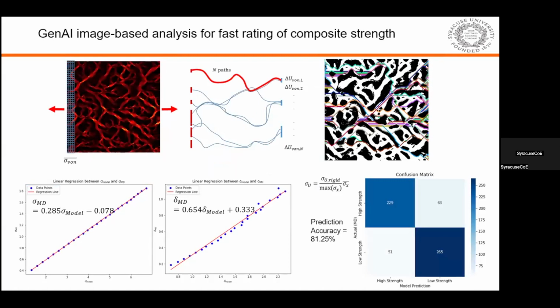So how to use those stress fields? We need to correlate that stress field to material property. We can take the stress field and do the average to calculate the applied stress, and then we can generate many paths, and based on the paths, we take the integral and calculate the amount of displacement. And then once we have the stress and the displacement of the sample, we can calculate the Young's modulus, and we can interpret the ultimate strength and toughness of the material. And then we can also evaluate the accuracy. So this is a confusion matrix between the actual MD result and the prediction from generative AI and the simple algorithm for mechanics calculation, to see that in most cases they agree with the MD output. So there's still some disagreement, but we are improving our performance.